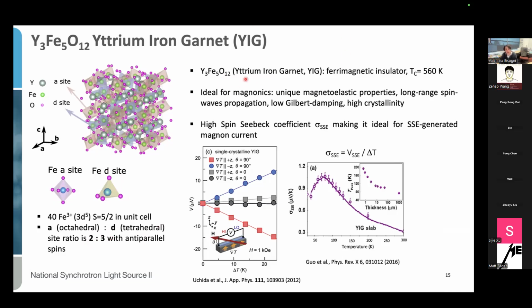So now Yttrium Iron Garnet is a very well-known material in the context of magnonics. And this is because of its unique magnetic properties. It has a very long range of spin wave propagation, ultra-low Gilbert damping, high crystallinity, so crystals can be made in very big dimensions. And for these reasons, it's highly used.